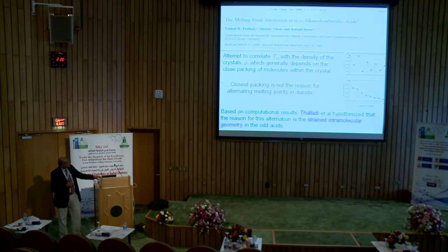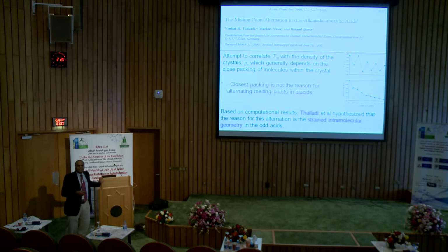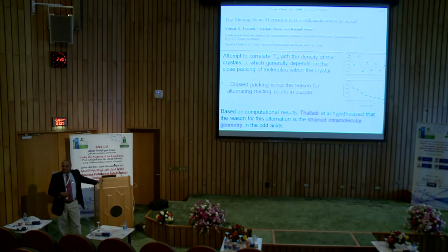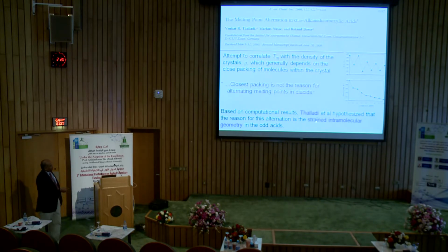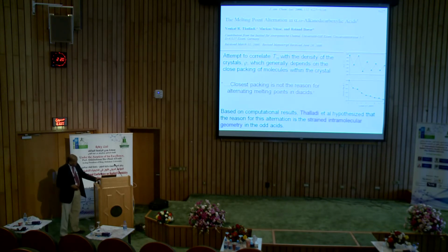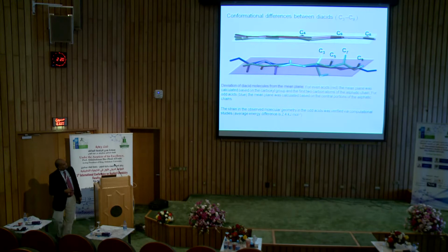Now, there are lots of different theories as to why this occurs. Conventional wisdom is that the density variation is what causes them. But then there was this paper in JACS. They say that density variation is not the reason. It's not the density. But this is because when you pack these things, the strained intramolecular geometry of the odd acids. Okay, now what do I mean by that?